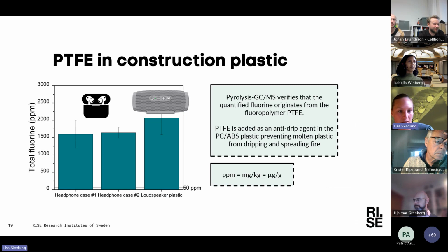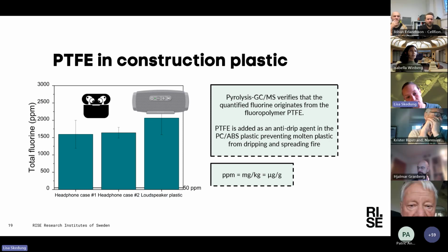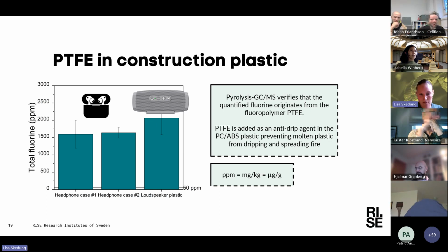But then when doing this analysis in different types of products, we could find PTFE in construction plastic. So we analyzed, this graph shows results from this kind of wireless headphone cases, two different ones, and also the plastic of a loudspeaker. You can see that the total fluorine concentration in this PC-ABS plastic was up to 2000 ppm. And the restriction limit is 50 ppm. And in this case, we could then verify that this fluorine actually comes from PTFE with pyrolysis GCMS. And this shows this other use of adding PTFE as a flame retardant or anti-drip agent in plastic.